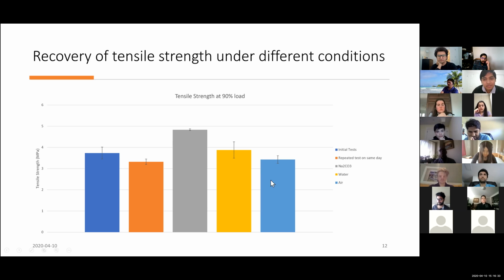And then this is water and this is air. So we can observe that sodium carbonate is able to enhance this split tensile strength after damage, and water is also performing better than air. And overall, in 3 days, all of the samples improve their strength a little bit. So this was one conclusion that I could draw from split tensile tests.